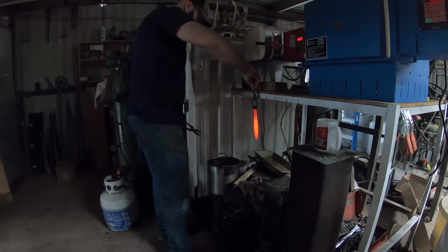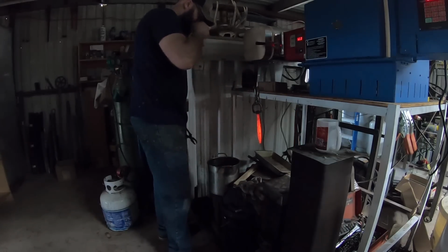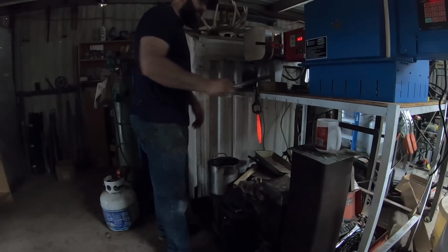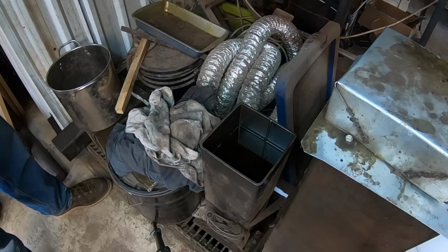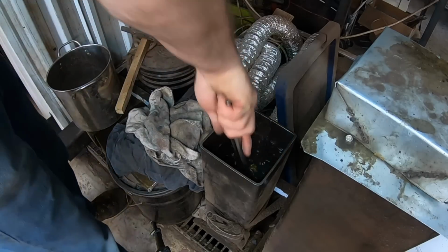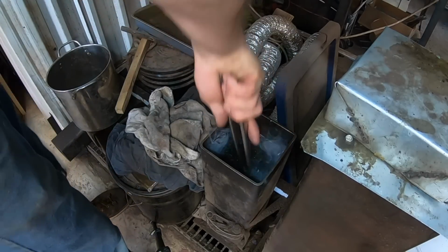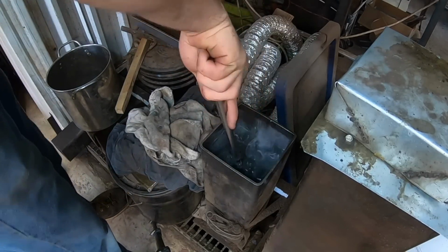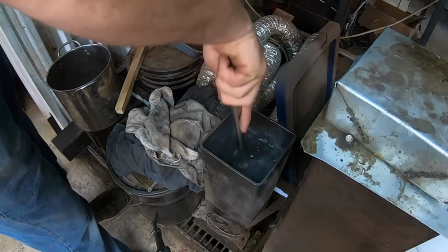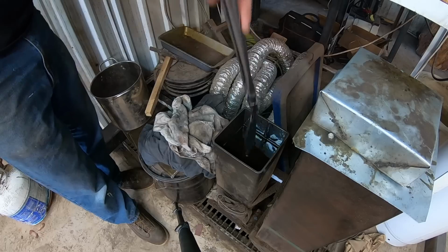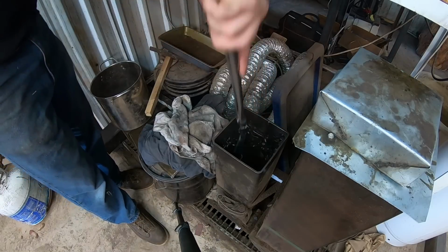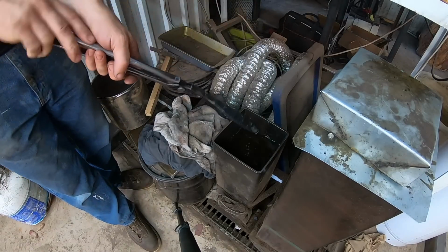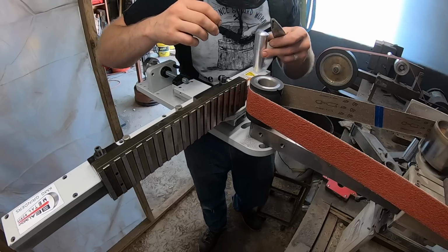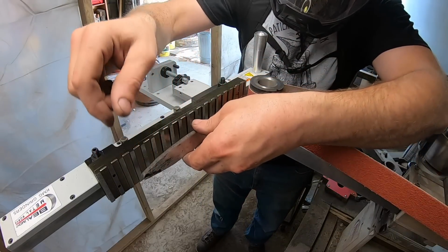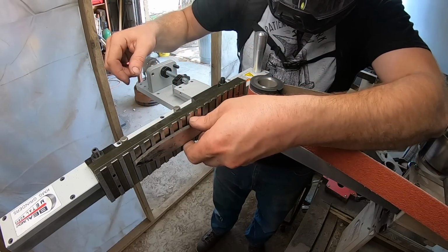So doing it this way, you can fully heat treat the blade before there's bevels on it. And at that point, everything is stable. Once you get it out of the temper, then you can go ahead and grind everything, and there's not going to be any further movement, at least very little, of the steel. So we did our normalizing and grain refinement cycles into the quench. It is all tempered now.